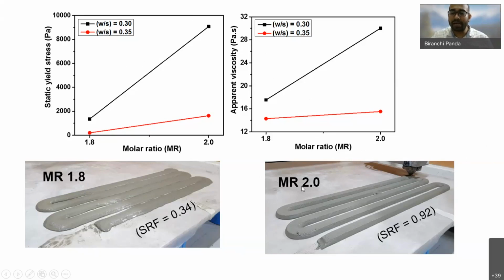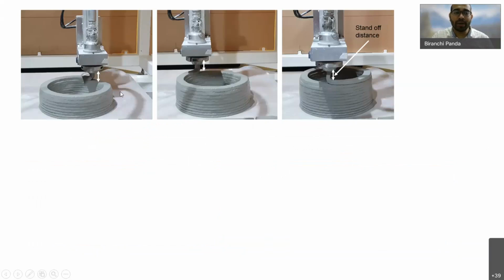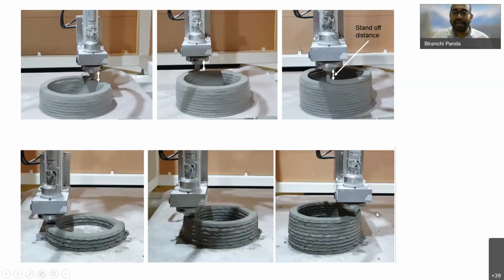Of course, if you want to add more layers, sometimes depending upon the material yield stress, the deformation will grow. What we have seen is that when you print a very poor material, after printing a few layers, this deformation height is going to increase. We call it stand off distance. As you can see, with more addition of layers, this distance will keep on increasing. But if the material is not deforming at all, it means all the layers are stable. You won't be able to find any deformation height between the tip of the nozzle and the top layer. So this is how the materials are always characterized for a final print.